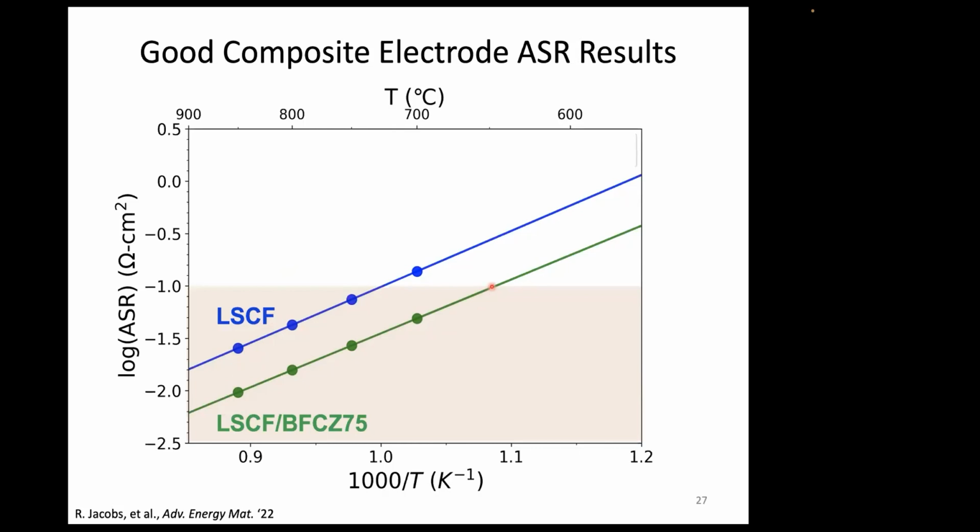So that gets you into the range of intermediate temperature fuel cells, which are around 600 Celsius. This was one set of experiments, so it's really not fully optimized. I think we could be confident that with a little bit of optimization, we could probably get this to perform at a commercially viable level at 600 degrees Celsius, which makes it an exciting material to consider for intermediate temperature fuel cells, which is where people are trying to take these.